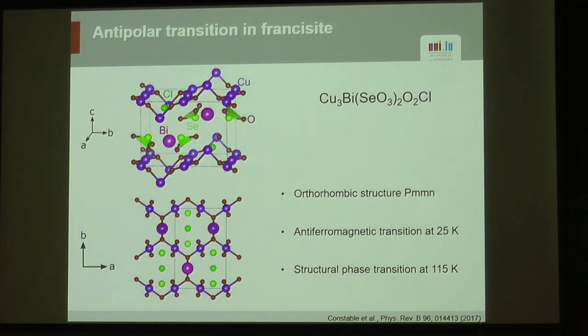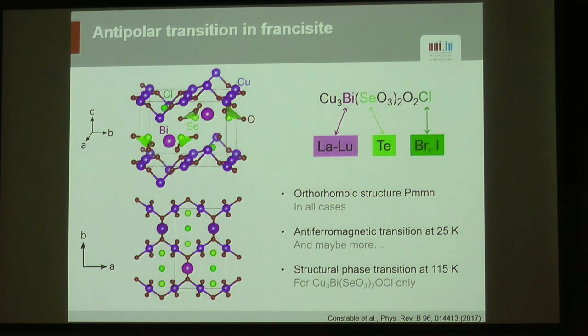With perovskites, we're very much making cation substitution. This is also something you can do. So typically what people have been doing is to substitute this bismuth by the rare earth, classically. Selenium here can be substituted by tellurium, and this chlorine can be substituted with other halogens. So there's been a bunch of compounds explored along those lines. In all cases, the high symmetry structure is the same, so this doesn't change much.